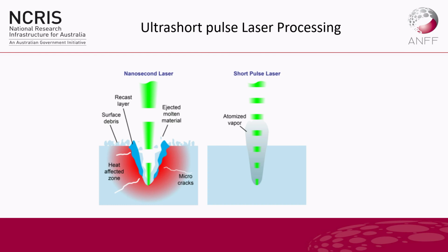Once you have lasers which are nanosecond or microsecond long pulses, the laser pulse is long enough to transfer heat to the surrounding material. And that generally has bad effects on what you're trying to do. It creates cracking, it creates molten edges and things like that. Whereas if you can use a short pulse, the pulse being extremely short, it won't transfer as much energy to surrounding materials, and you can start to ablate very well-defined features.